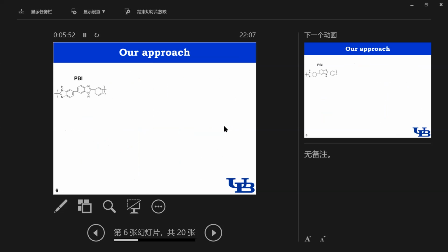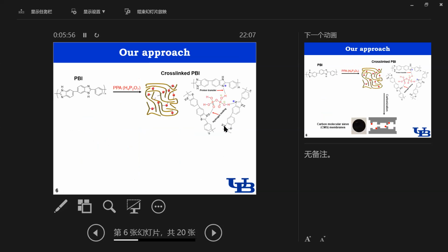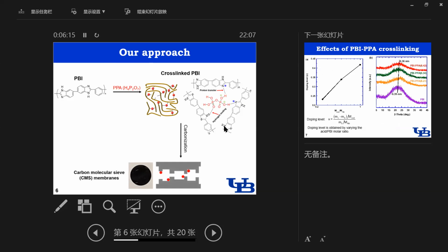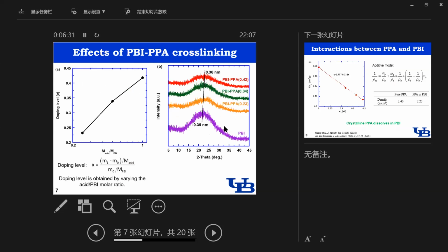So here is our approach. First, we use pyrophosphoric acid to dope PBI with hydrogen bonding and proton transfer. As pyrophosphoric acid has more acid groups and can generate more hydrogen ions, this doping can be better than PBI with phosphoric acid. And then we carbonize those doped PBIs to create more free volume for gas transport at a low carbonization temperature, say 600 degrees C. Firstly, we use doping level to represent the doping degree of PPA in PBI, and we get varied doping levels by changing the acid PBI molar ratio in the acid doping solution.